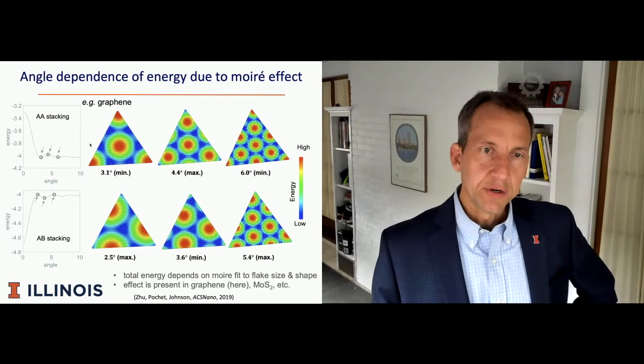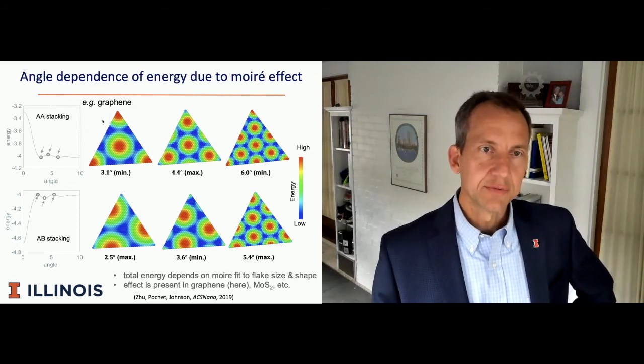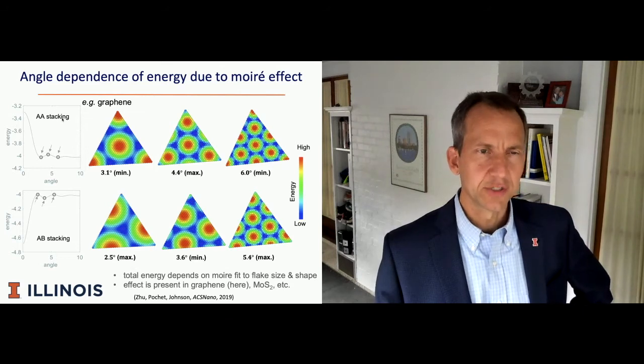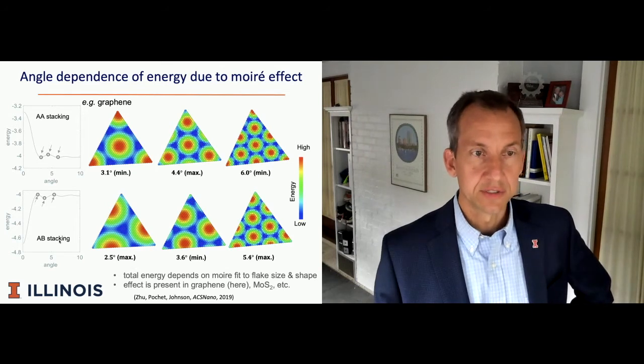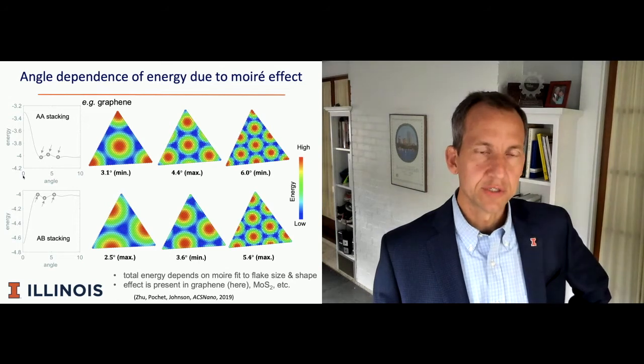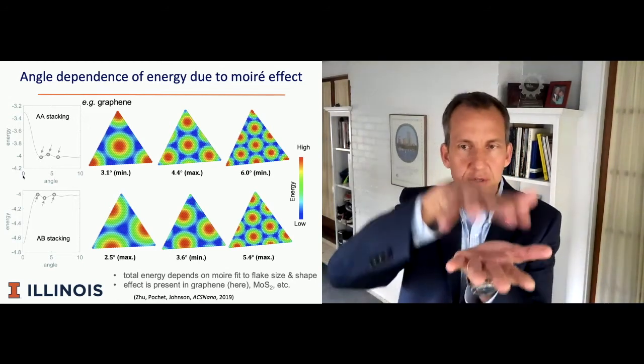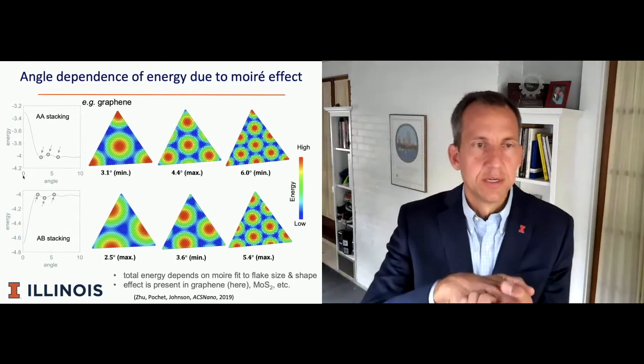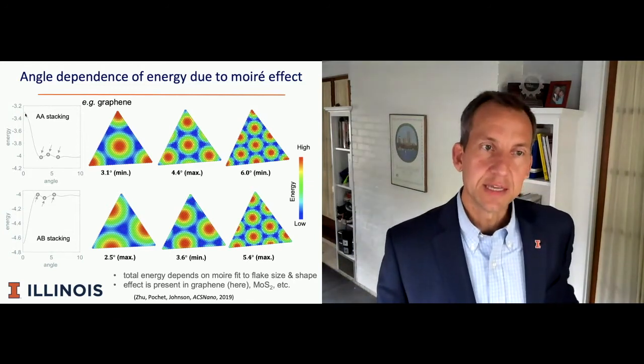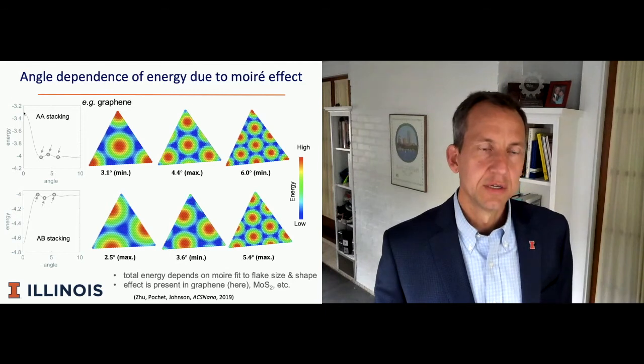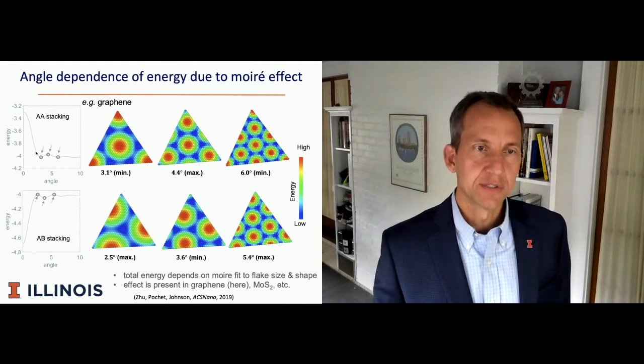So what we see here, for the case of graphene, is two alternate stacking starting points: AA stacking, which is actually a higher energy stacking to start with, and AB stacking, which is a lower energy stacking to start with. And when I say to start with, I mean from zero angle rotation. So if you start with the graphene triangle on the graphene substrate with zero angle rotation, in the case of AA stacking, it has high energy. And we can map the energy surface through the angle degree of freedom. We find that there is a local minimum at about 3.1 degrees.